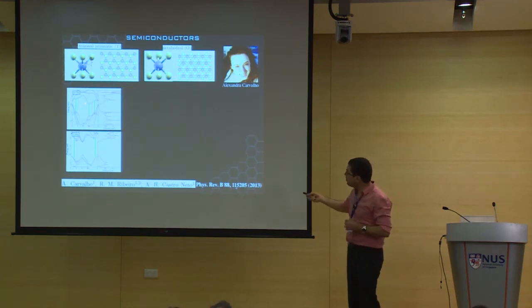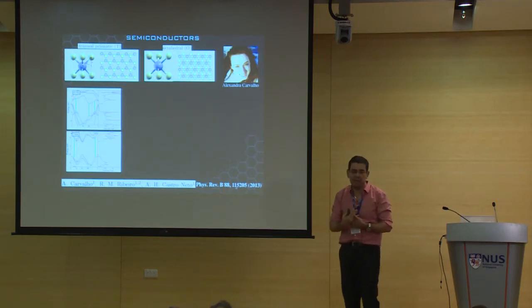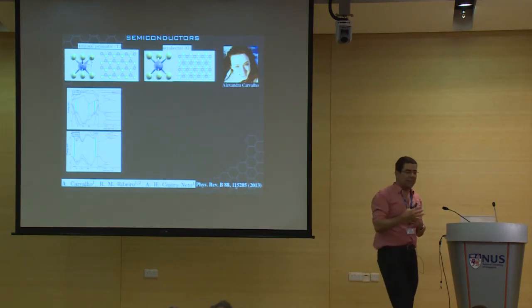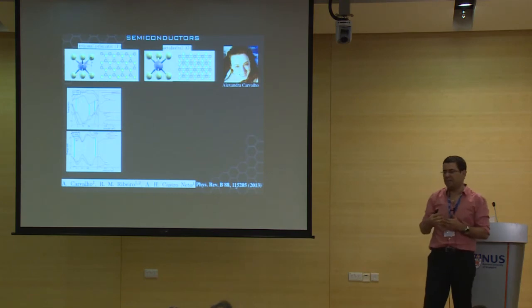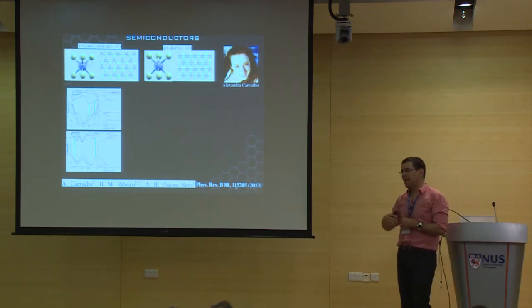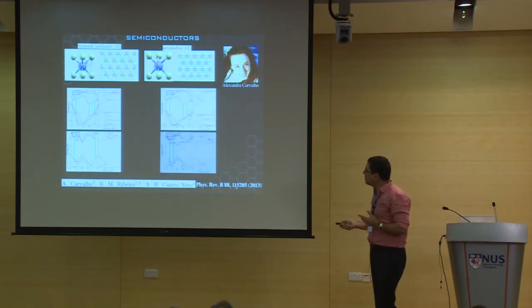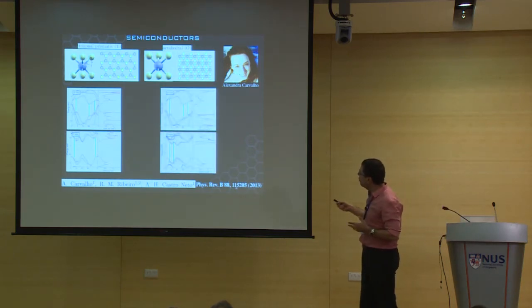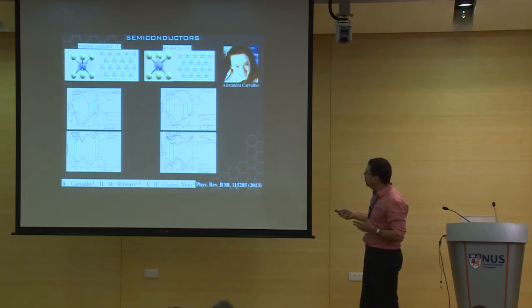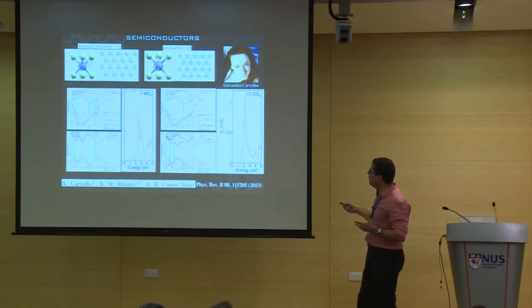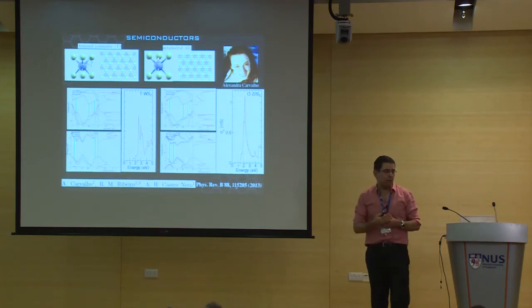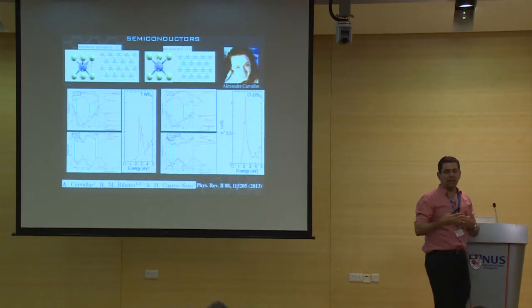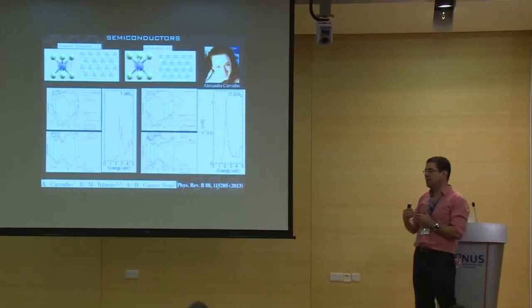This is coming from band nesting: the conduction and valence bands in these materials, in certain regions of momentum space, nest extremely well with each other. That's what produces a huge peak in the conductivity. Alexandra has calculated this for other materials too, such as zirconium disulfide, and when you compute the optical conductivity, you see these huge peaks, which are due exactly to the band nesting structures in the band structure.